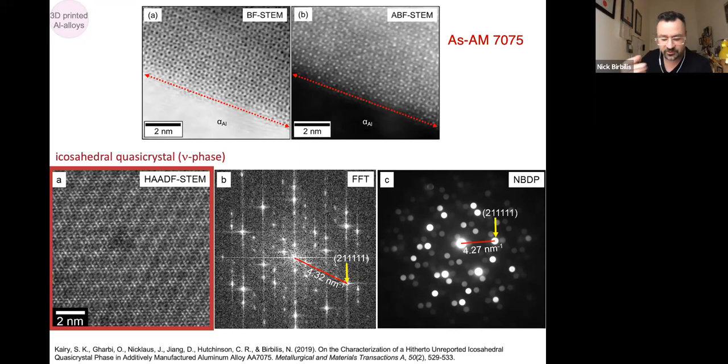And when you go through the process of STEM and then Fourier transforming your image, you can see that this is what's been determined to be a previously unseen phase. So what we're seeing in additively manufactured 7075 is not the conventional hardening phase, which is eta phase, which is MgZn2. But it's actually a zinc copper magnesium phase that had no name. So we called it nu phase, not because it's brand new, although that would have been funny, but just after the Greek letter for n, nu.